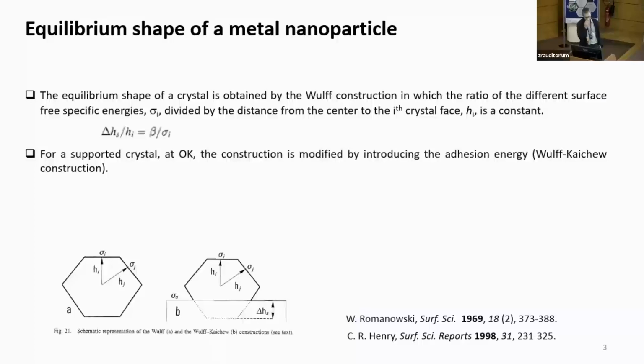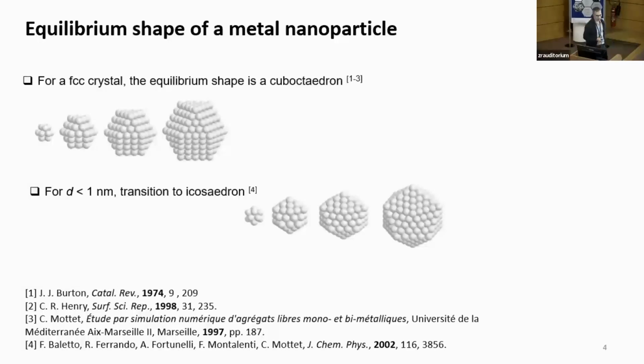Okay, so let me start with thermodynamics. What we learned is that the equilibrium shape of the platinum nanoparticle is determined by the minimization of the surface energy. And for a face-centered cubic structure, you would get mostly 111 and 100 facets, because those facets minimize the surface free energy. So this is why for particles of 5 nanometer in size that we are using in fuel cells, you have these 111 and 100 facets. And there will be a transition to an icosahedron when you go below a certain size, which was roughly estimated to be 1 nanometer. There you have only 111 facets.